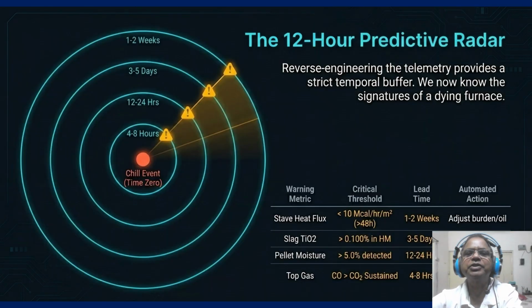So the 12-hour prediction radar. We have reverse engineered this failure into a strict temporal buffer. Look at the radar ring. We now know the signature of a dying furnace. Stave Heat Flux gives us a 1 to 2 week lead time if it flatlines, so we adjust the burden slag. Titania gives us 3 to 5 days to remove ilmenite. Pellet moisture gives us a 12 to 24 hour window to add coke. Finally, top gas scrubber gives us the last chance, a 4 to 8 hour window for an emergency wind cut.